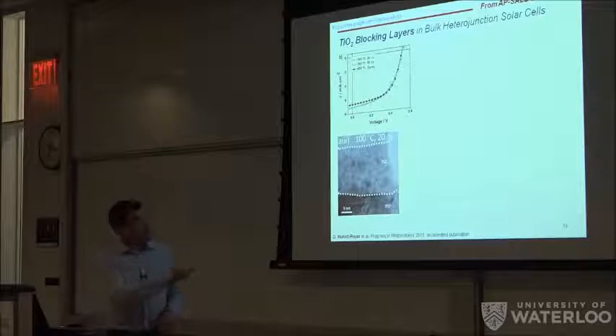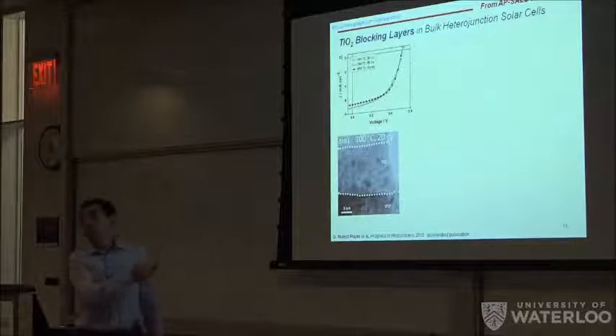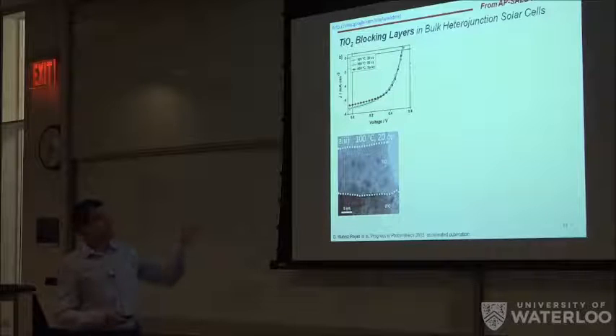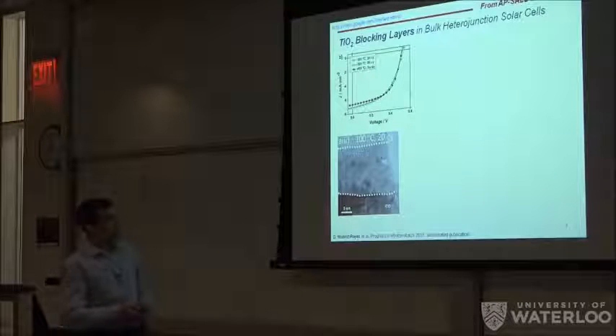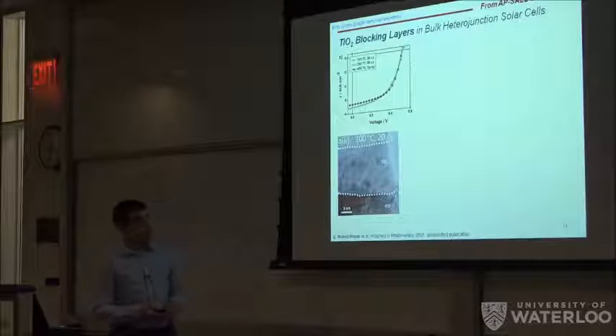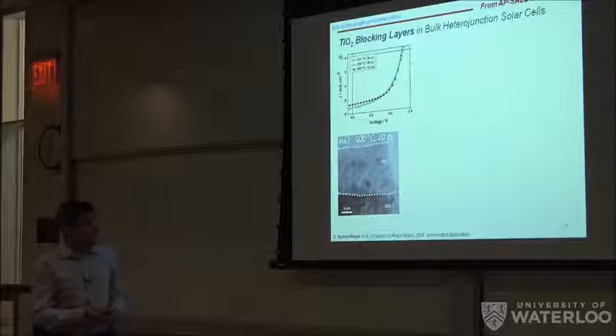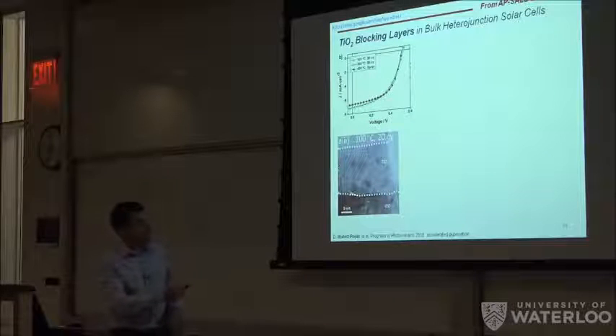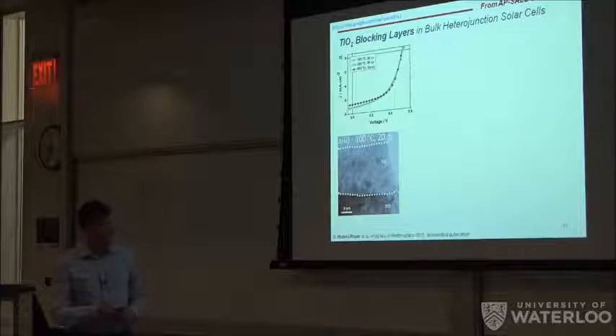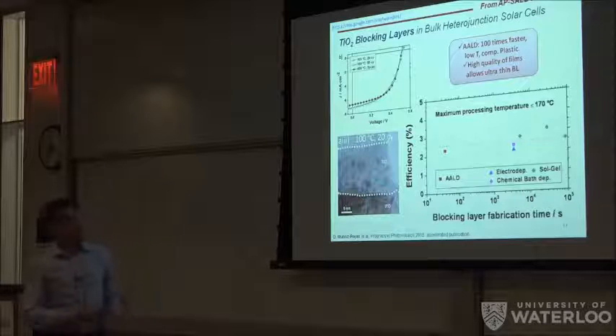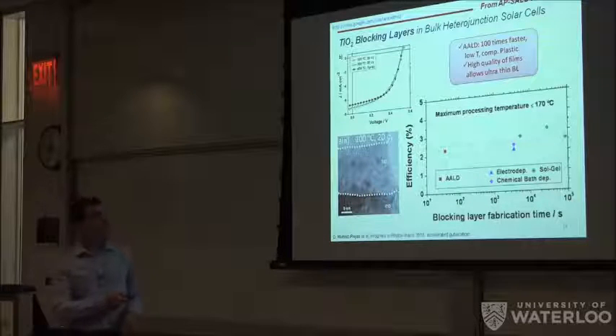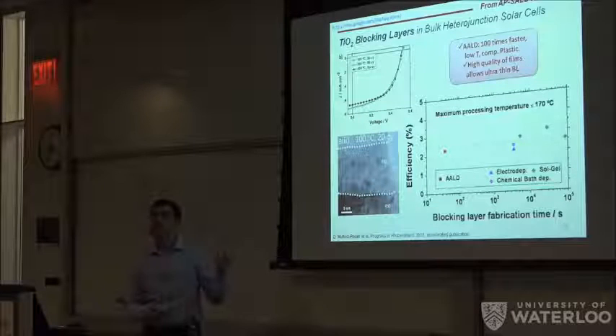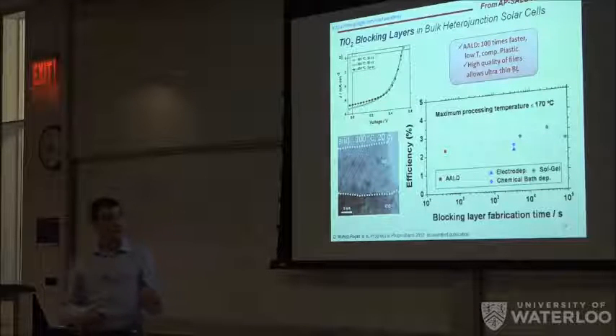So when we compare the results, you can see that cells fabricated with the 3 layers perform the same way. So ALD is as good as spatial ALD as spray pyrolysis. And you can see here the thin layer of TiO2 made at 100. But the good thing here is you compare how long it takes to deposit this layer compared with other processing methods done at low temperature and ambient pressure.